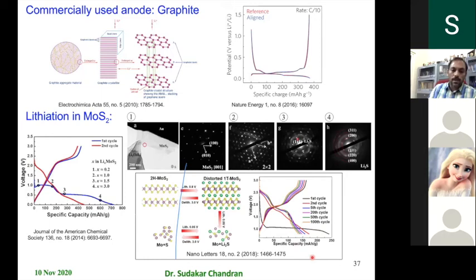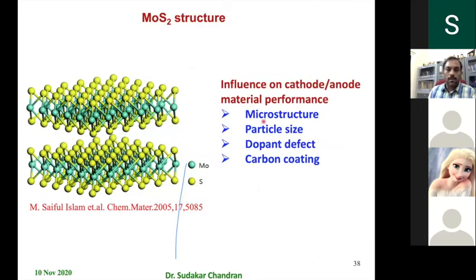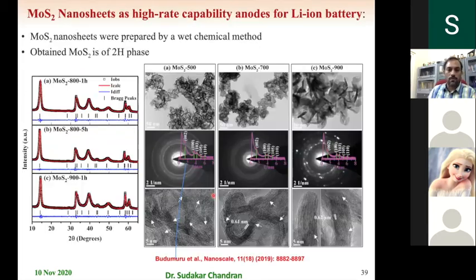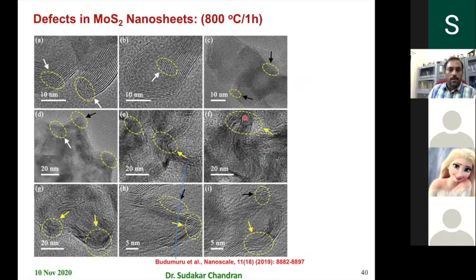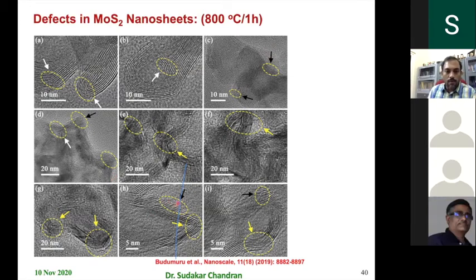So we explored the properties in moly disulfide. In fact, it gives all this tunability, microstructurally you can tailor, size you can tailor. You can also coat it with certain carbon material. So this is what I showed. So we took the same 3 samples, and I will show to convince you how the defects are. See, these are all the bending defects, and then the curling defects. The edge defects are shown. Some of the edge defects are shown. So in these regions, always the sheets terminate. Therefore, you have the one-dimensional defects that I mentioned.